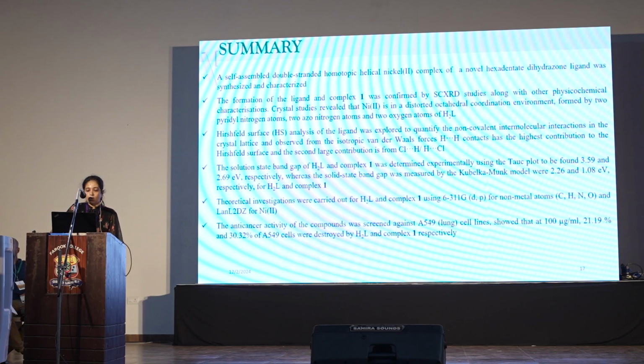Hirshfeld surface analysis of the ligand was explored and found that the H...H contacts are the highest contribution to the Hirshfeld surface. The solution state and the solid-state band gap of both the ligand and complex 1 was determined. And the anti-cancer study of the compounds screened against A549 lung cancer cells shows that at 100 microgram per ml, 21.19% and 30.32% of the lung cancer cells were destroyed by the ligand and complex respectively.